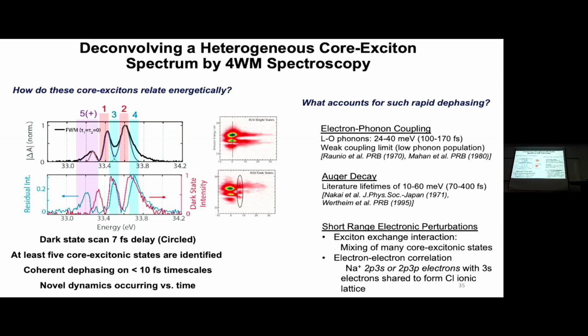And so we started going back to think about the linear spectrum, which is the black line, and fitting the linear spectrum, and then realizing if you collect all the data at the different time delays, instead of just being 3 big features, there's at least like 5 features underneath here. So you understand that there's a lot more underlying these features when you see these core excitons.